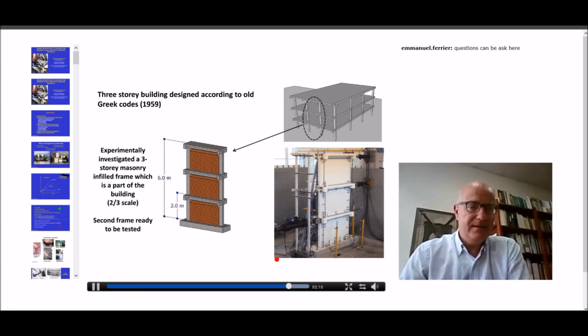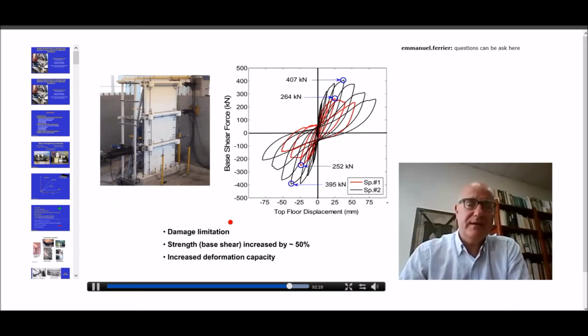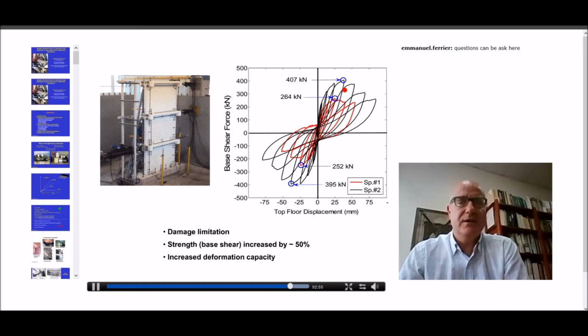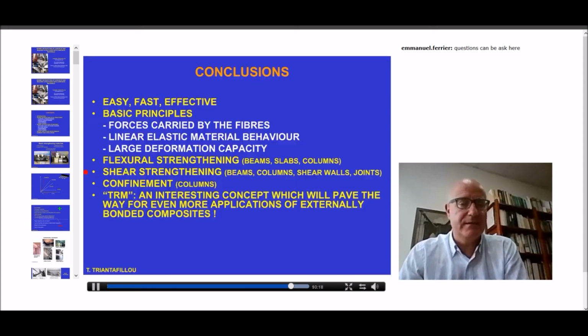This has been tested in nearly full scale relatively recently. You see, for example, a 3-story, nearly full scale reinforced concrete frame with masonry infills. The frame was tested without any strengthening, and the response is illustrated by the red curve. And also after strengthening with those textiles, after covering the area of the walls and the surrounding frames with those textile-based materials, that is illustrated by the black curve. You can clearly tell the difference. The damage is limited, is reduced. The strength is increased by nearly 50% in that particular example. The deformation capacity also gets higher. So it is really an interesting concept for the case of infills in reinforced concrete frames.